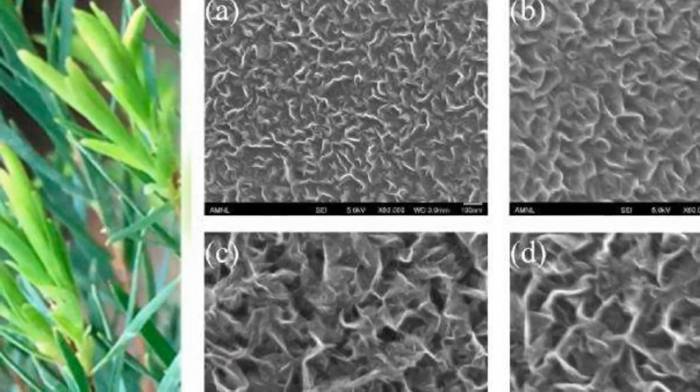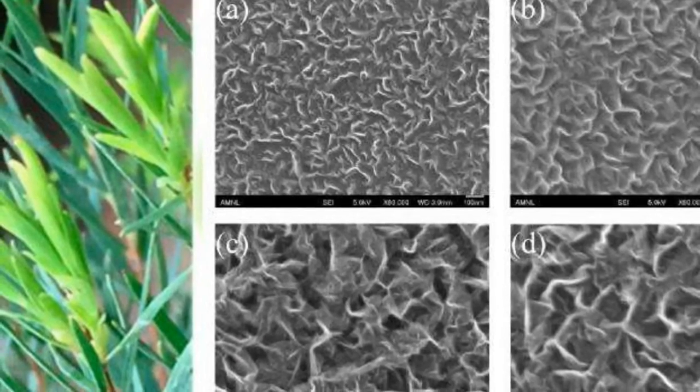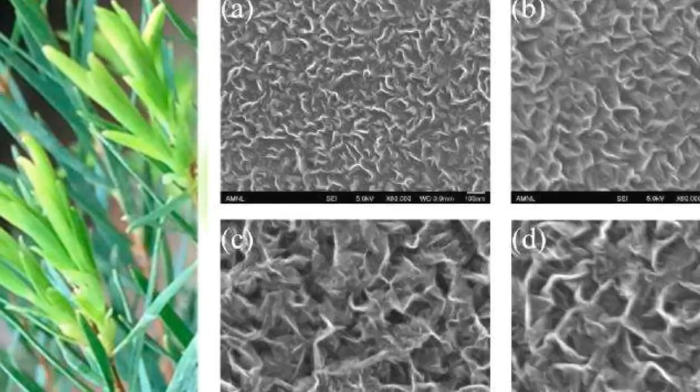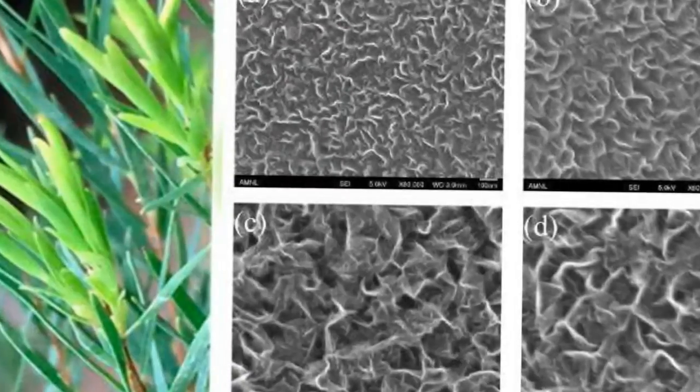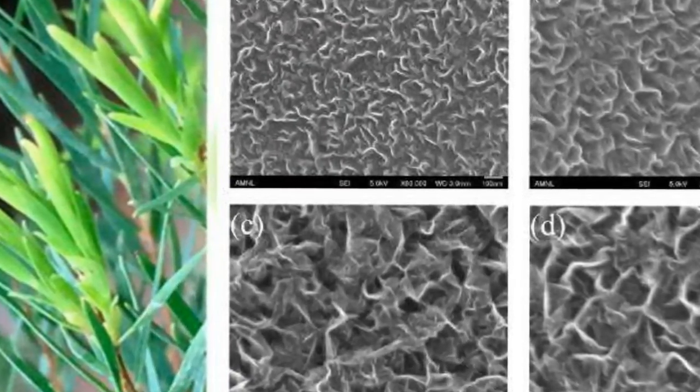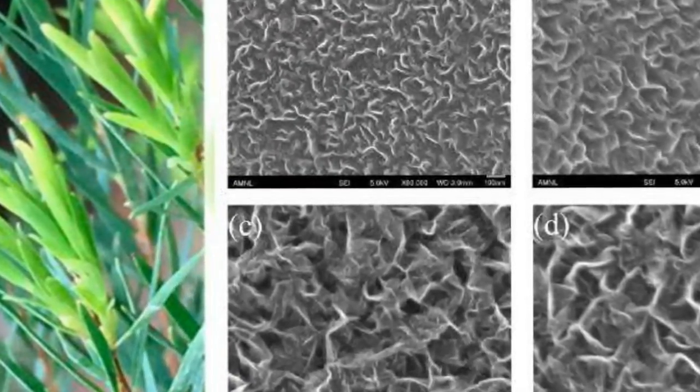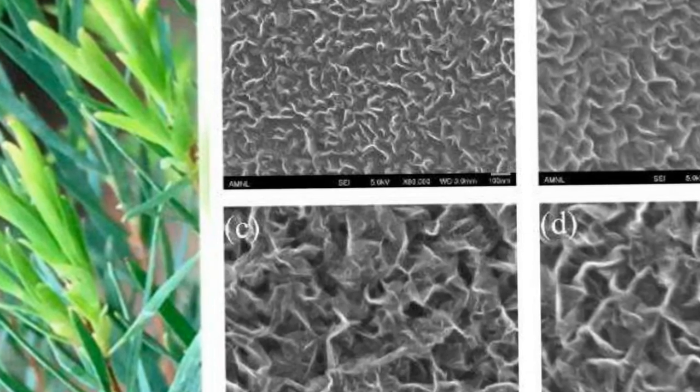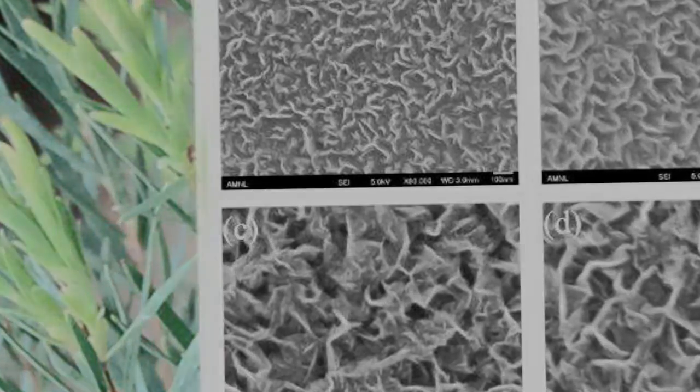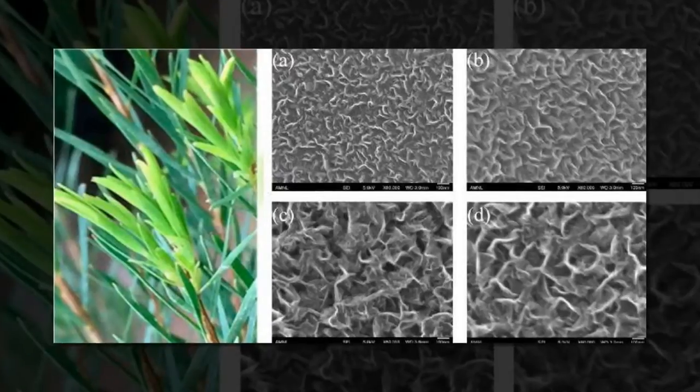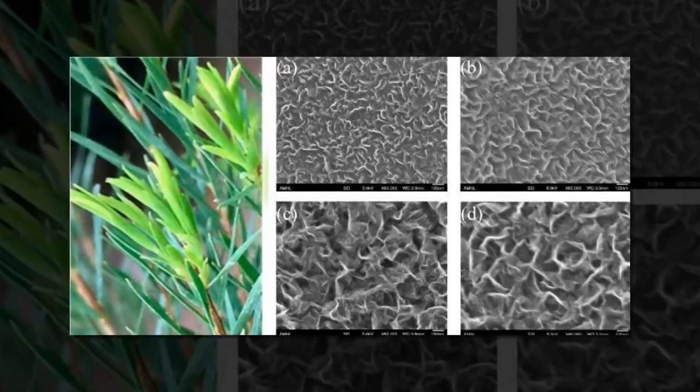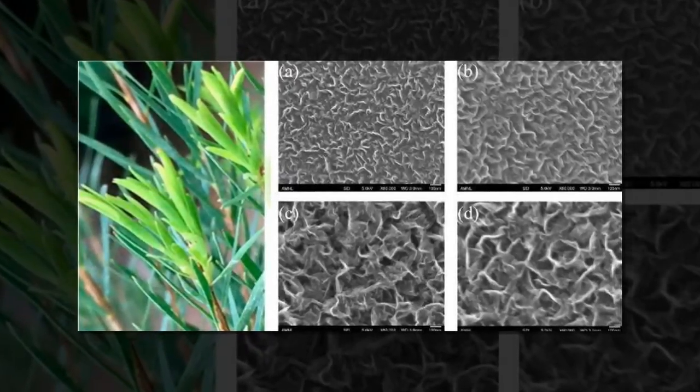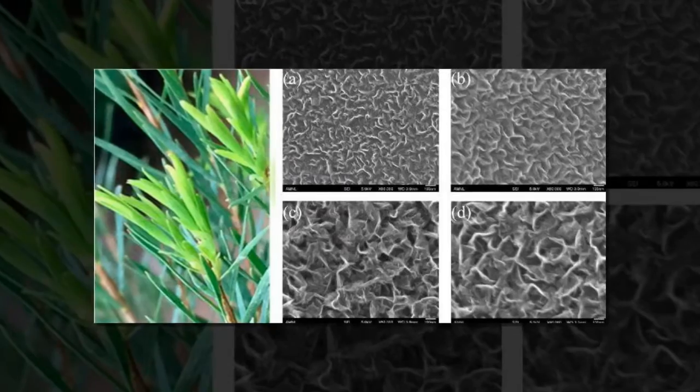In a new study, researchers have grown graphene from the tea tree plant Melaleuca alternifolia, the same plant used to make essential oils in traditional medicine. The researchers demonstrated that they could fabricate large area, nearly defect-free graphene films from tea tree oil in as little as a few seconds to a few minutes, whereas current growth methods usually take several hours.